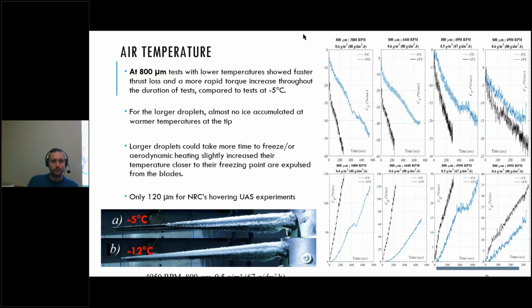And what could explain this is that the larger droplets, due to higher thermal inertia, take more time to freeze and have time to be exposed to the higher centrifugal force toward the tip of the blade before they are able to completely freeze on the blade. Next slide, please.